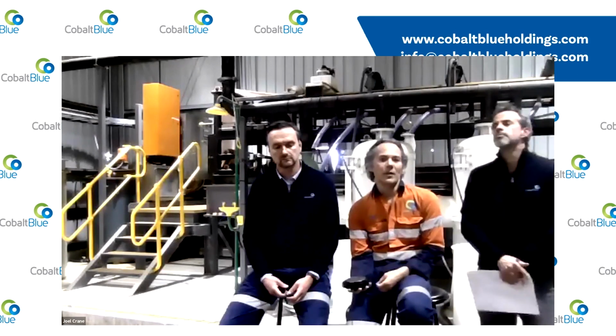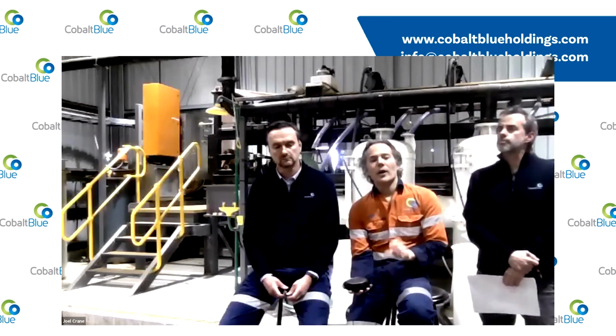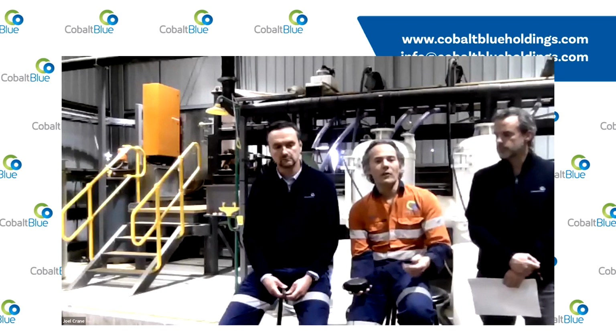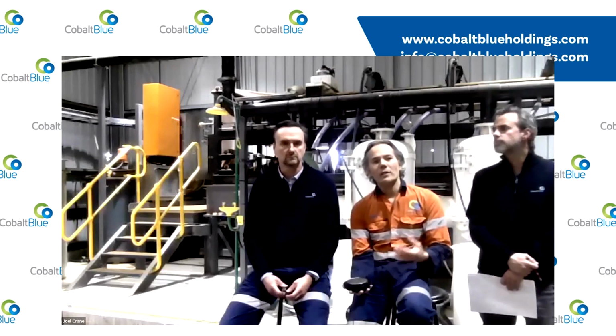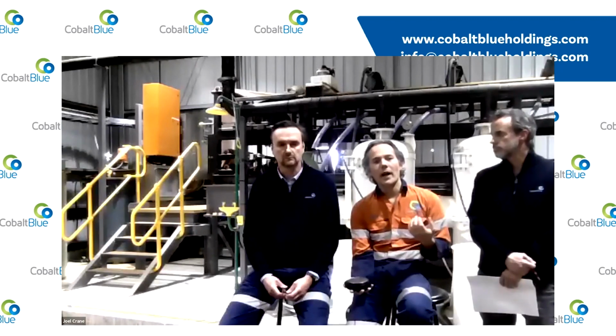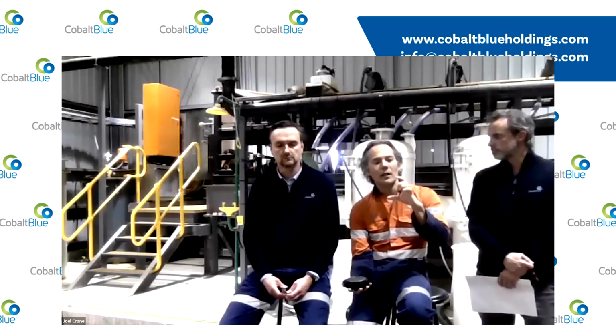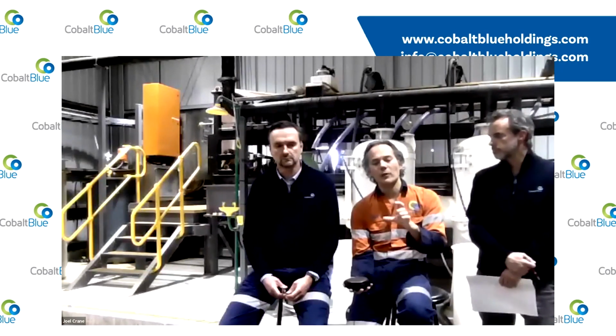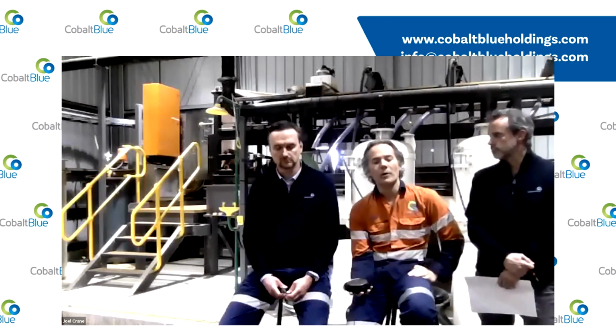came from drill samples. So when you drill the sample, you end up with a lot of fines by way of drilling and breaking the rock down, whereas now we're taking the mine ore, so a bit of drill and blast, pull it out, put through the crushers, and then we have a much higher, larger particle size distribution versus the historical stuff that was a lot finer because it came from the drill bit.